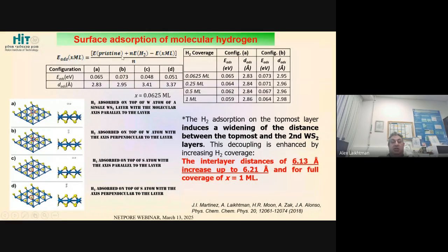And they calculated by DFT different structures from pristine nanoparticles or nanotubes to hydrogen adsorption. And then they calculated the adsorption energy. And in the case that adsorption energy is positive, it means that the adsorption process is favorable. If it's negative, it's not so favorable. So they started their calculation with just physisorption and different types of hydrogen configuration on top of WS2, either nanotubes or nanoparticles. I'm not showing you all the results and all the structures, but just to have an impression. And for hydrogen coverage in fractions of monolayer. And then you can see that in this case, the energy is positive, so the adsorption is favorable.